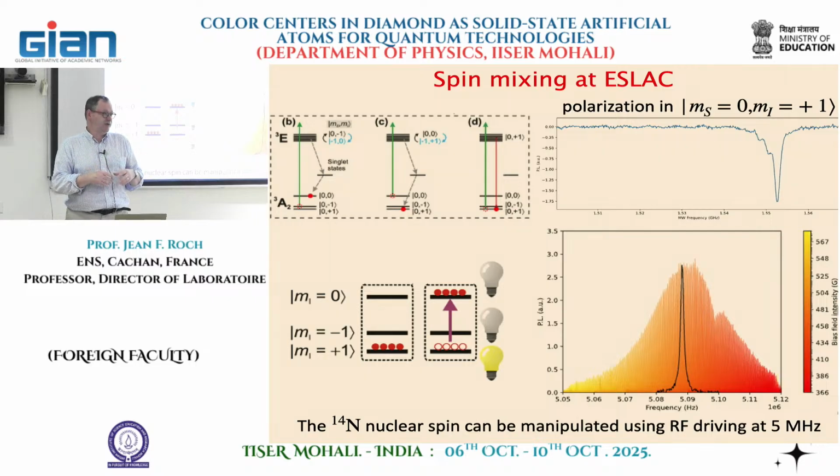Suppose you would have a crystal and you polarize very efficiently the NV. That's not difficult to do. Just send a lot of green light on it. And then, using this trick, you transfer the population to the carbon-13. But now there are other possibilities. Once you have this nuclear spin of the diamond, you can put a lot of carbon-13 by, for instance, growing with methane enhanced in carbon-13.